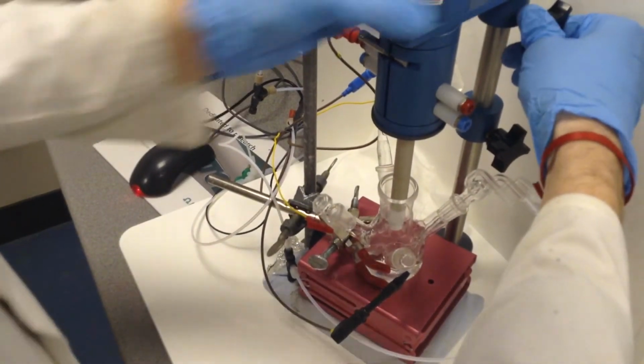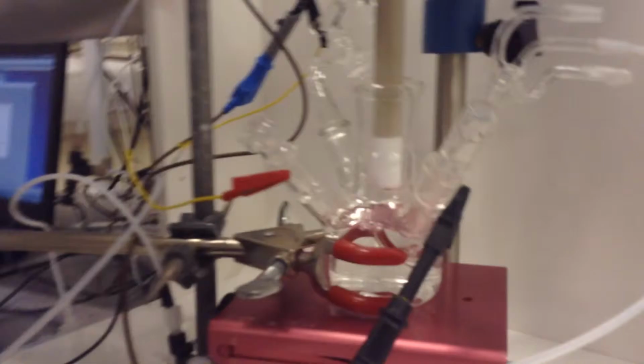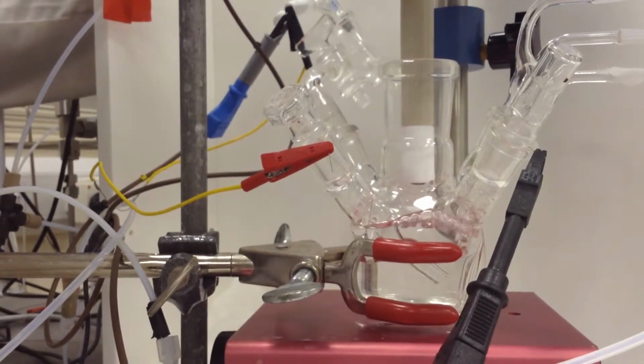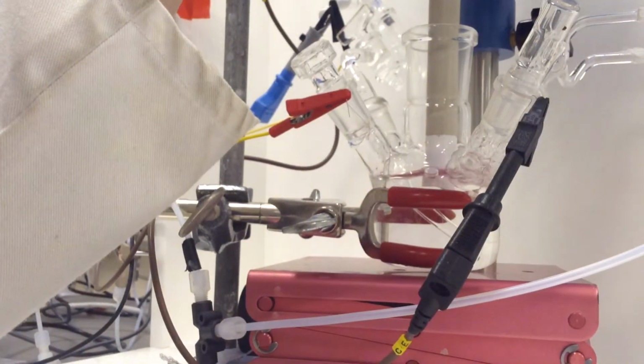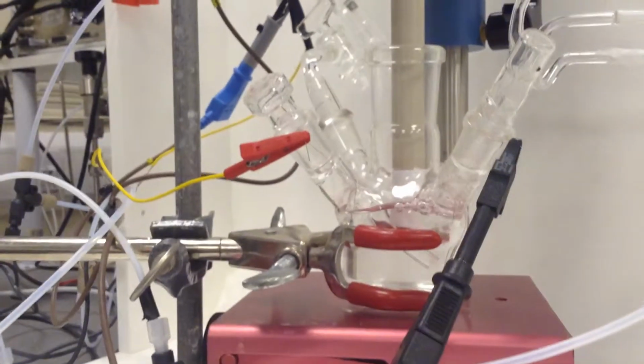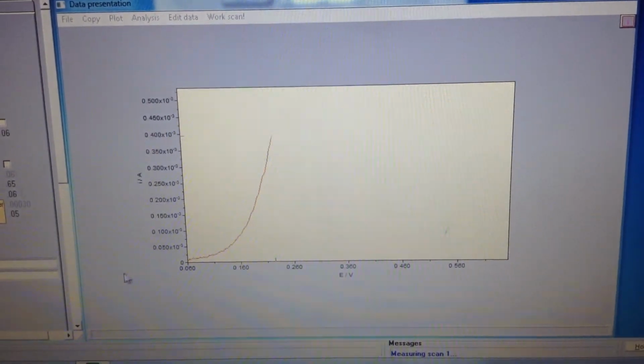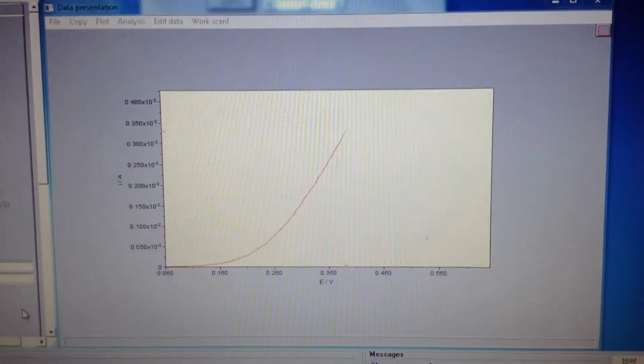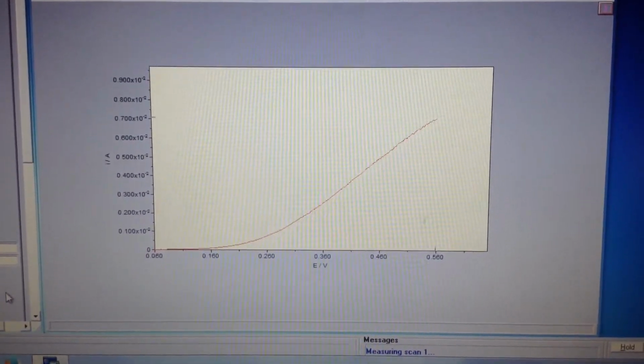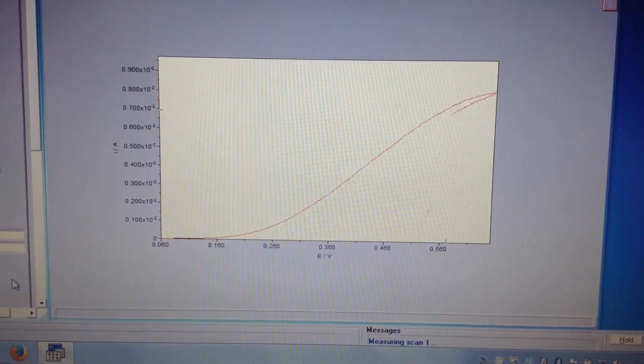So now we insert our electrode in the electrolyte, and we are going to rotate the electrode too. At which rotation rate are we going to cycle, Javi? 1000 RPM. So as you can see, the formic acid oxidation starts at really early potentials. This voltammetry is being done at 50 millivolts per second.